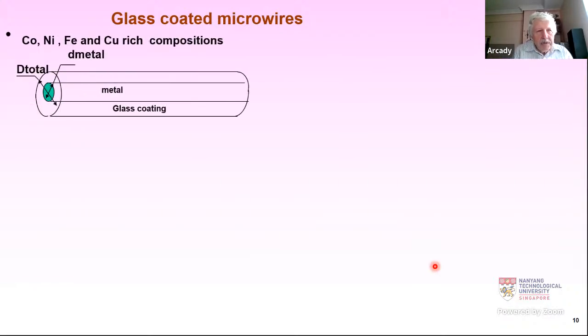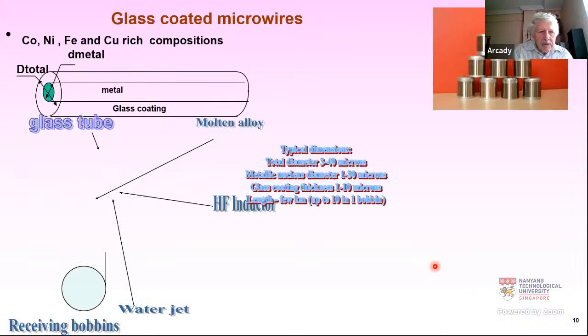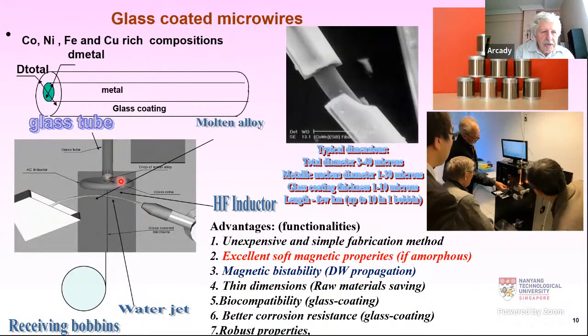In our laboratory, we are working mostly with so-called glass-coated microwires, which could be produced by rapid quenching from the melt. You can see the schematic picture of the fabrication facility. First we prepare the metal ingot with the desired composition, then we melt it by an inductor, and then draw first a glass capillary, and then the metal fills this glass capillary, and then we can form these quite uniform magnetic microwires. Typically, the diameter of the microwire is in micrometers, and the length could be up to a few kilometers of continuous microwire. And they have some different properties.